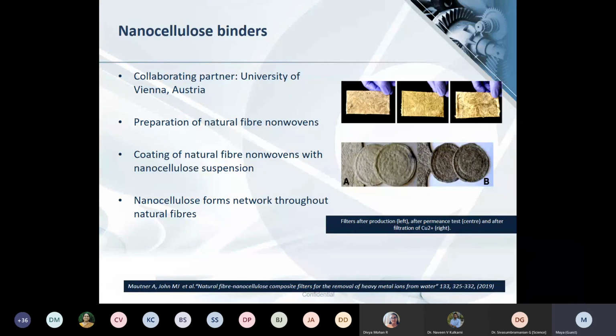So there is no external polymer matrix here. It's just an all cellulose composite, one could call it, because it just comprises of the natural fiber nonwovens and a nanocellulose coating. And the Austrian partners tested these materials for use as composite filters for the removal of heavy metal ions. I think we published a paper last year on that, and it was found to be quite successful.